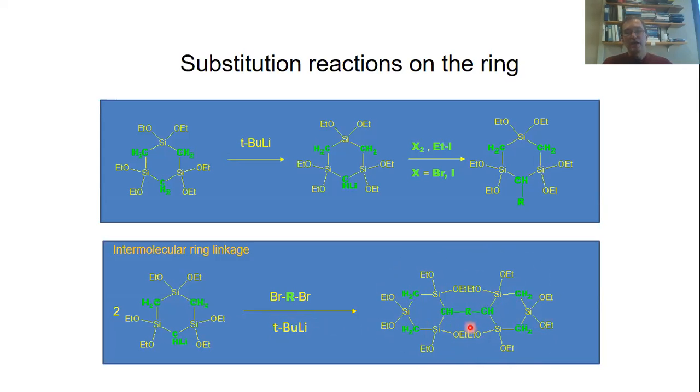An interesting aspect here is also that the R group that can be incorporated can be an alkyl group which is longer than just 2 carbon atoms. I told you previously that when you want to place a propyl group into a standard silsesquioxane precursor, the self-assembly doesn't work anymore. But when you place the same propylene group in between these 2 rings, then you can still self-assemble a periodic mesoporous structure from the respective precursor.